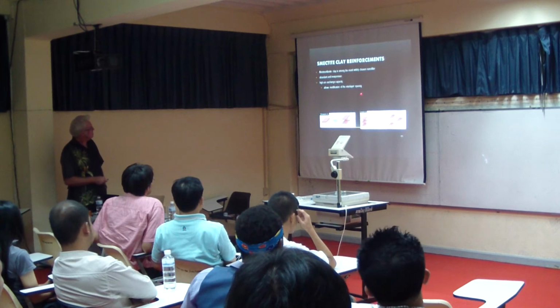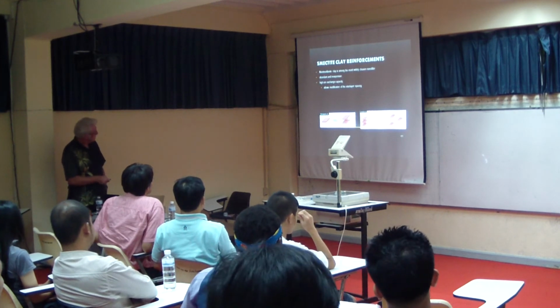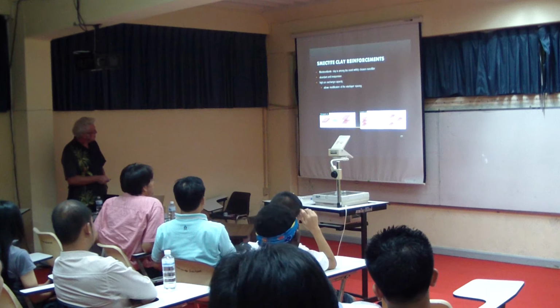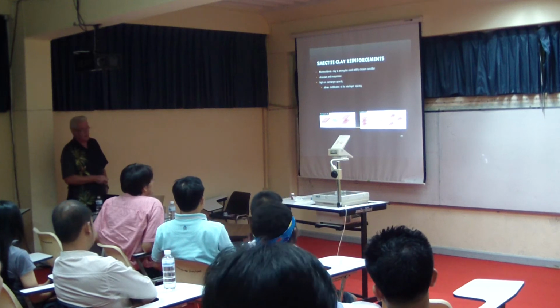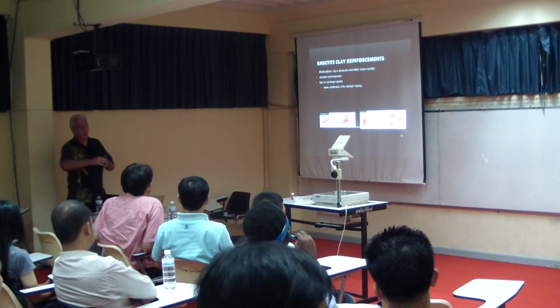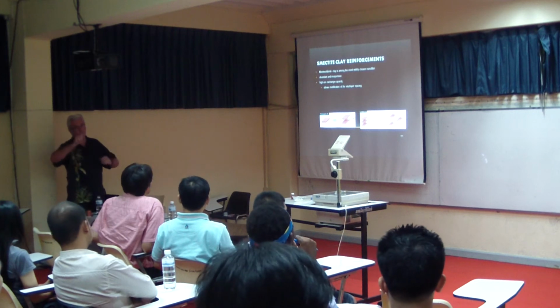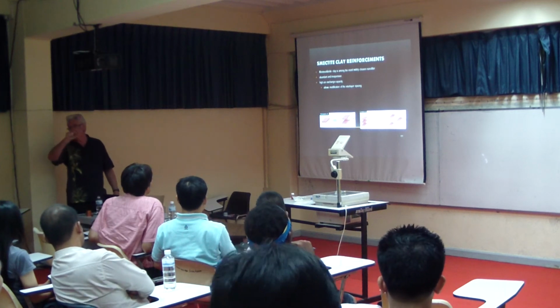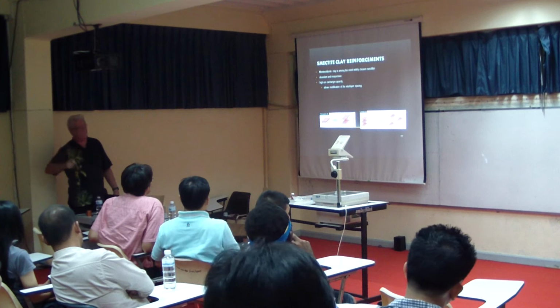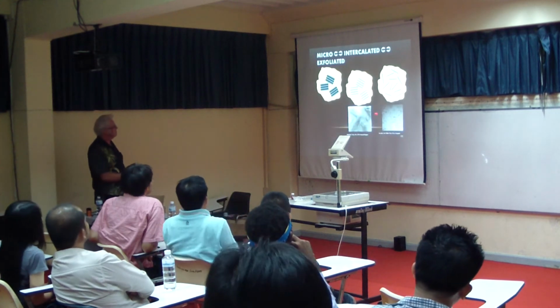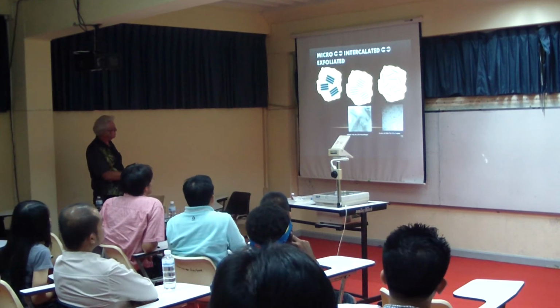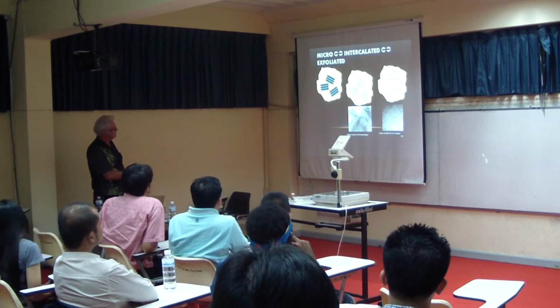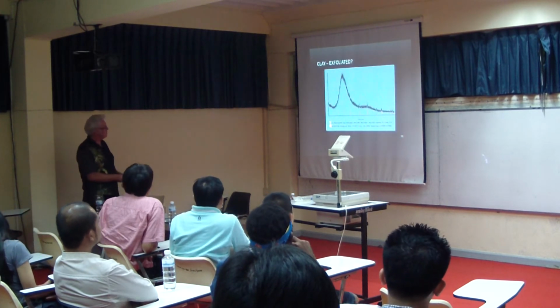So we've done some work. We can use clays. Clays are a layered structure. If we're very clever, we can exfoliate the clay layers, so we have a single clay layer, just like a graphene sheet. And we can use those. And we get this, as opposed to that. And this gives some very interesting properties.